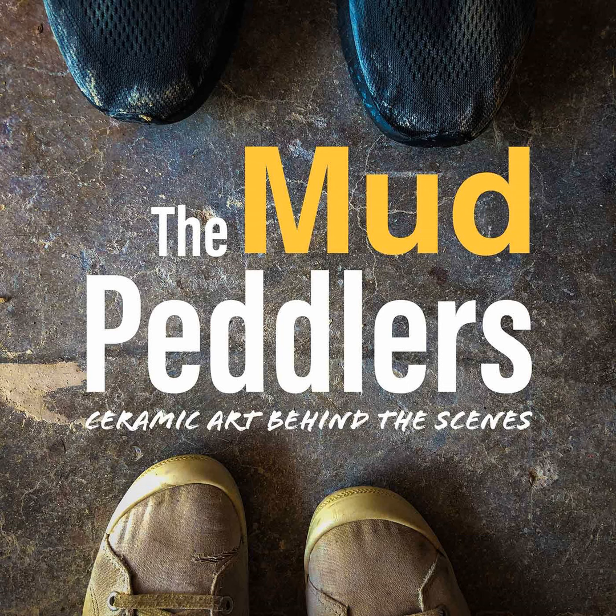Some things in the glaze react further under longer heat work. I love doing a slow cool — some of my matte glazes come out more matte with a slow cool because the alumina is allowed to develop and react over a longer period of time. Those are the kinds of things that develop micro-crystals in a matte glaze. Most crystal glazes actually require a slow cool — I've seen potters do holds for like an hour at cone six or even a four-hour hold between 1700 and 1600 degrees Fahrenheit.